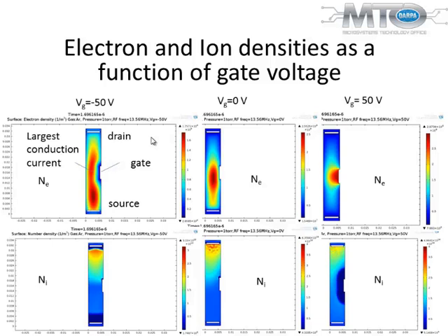If you compare, for example, this one to that one, we are looking at the ion densities. You can see that for this particular case, we have repelled the ions from the surface of the region, and here we have attracted them. This is the scale. So this is effectively programming the doping in semiconductors.